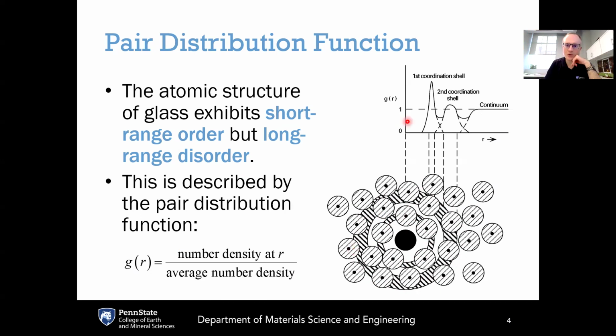Now, what the pair distribution function does, this g(r) function, which is plotted on the y-axis, is that it plots the number density of atoms found at r divided by the average number density in the limit of long distance.